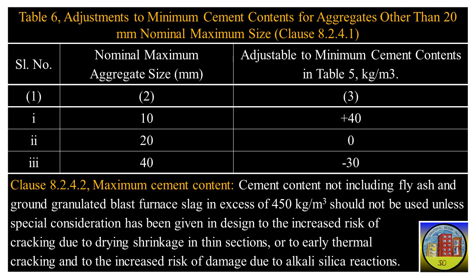8.2.4.2. Maximum cement content not including fly ash and ground granulated blast furnace slag in excess of 450 kilograms per cubic meter should not be used unless special consideration has been given in design to the increased risk of cracking due to drying shrinkage in thin sections, or to early thermal cracking and to the increased risk of damage due to alkali-silica reactions.